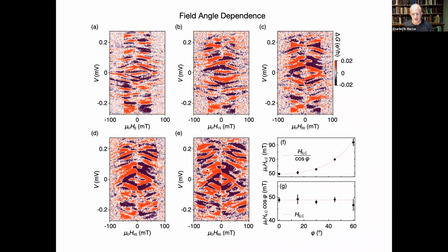But now something interesting. If I turn the magnetic field 15 degrees, and then 30 degrees, and then 45 degrees, and then 60 degrees off axis, what you see happening is systematically the coercive field, the size of the window, grows correspondingly. Why? Because the only part of the field that matters is the part of the field that's along the wire. There's an easy axis, and all that's happening is it's getting magnetized along its easy axis, and the out-of-plane component of the field doesn't matter.